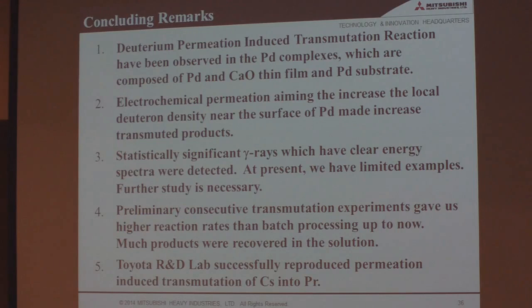So I would like to conclude. First, deuterium permeation-induced transmutation reactions have been observed in the palladium complexes, which are composed of palladium and calcium oxide thin film and palladium substrate. Second, electrochemical permeation, aiming to increase the local deuterium density near the surface of palladium, increased transmuted products by about 2 or 3 times or more. Third, statistically significant gamma rays which have clear energy spectra were detected. At present, we have limited examples. Further study is necessary. I still continue this gamma ray observation.